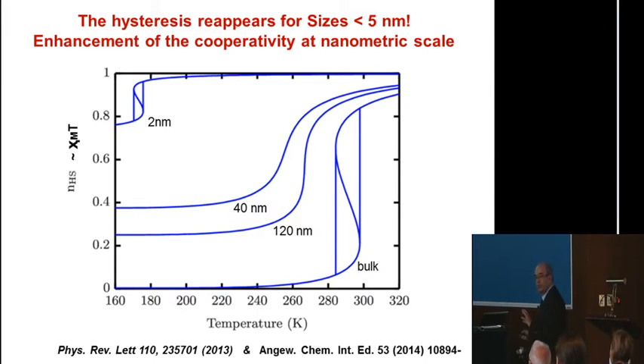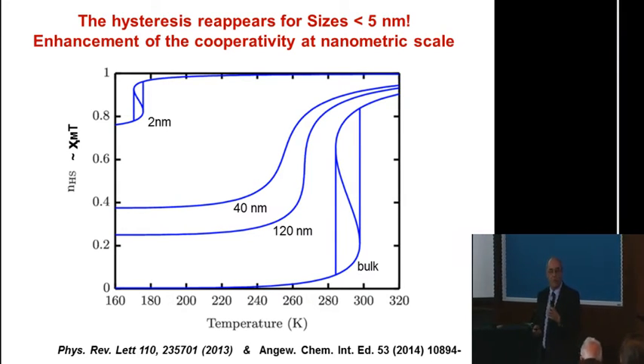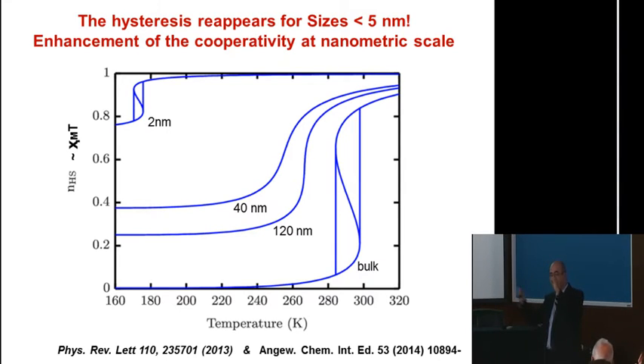What I would like to tell you here is that through this preparation, because we prepared spin crossover nanoparticles, we can study the effect of the size of the molecules on the hysteresis loop, on the memory effect. Why did we want to do this? As I told you, molecules are interacting between them. So the number of molecules is important. If you decrease the number of molecules because you are decreasing the size, then you can lose your hysteresis loop.